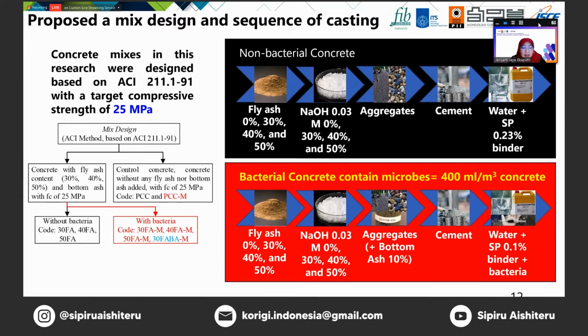We made a certain sequence of mixing of the materials during casting. It is very important because it will affect the workability of concrete. We place fly ash first, then mix with the sodium hydroxide, and then continue with all aggregates, followed by cement and superplasticizer, and also add water containing superplasticizer in the final mixture, and also we put the bacteria. And we make a different superplasticizer between the black and the red here. Black is the non-bacterial concrete, and the red contains bacteria,